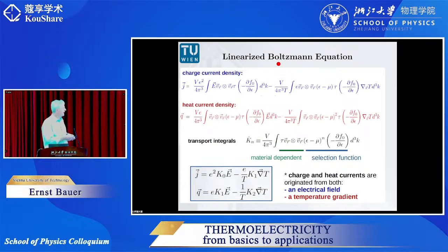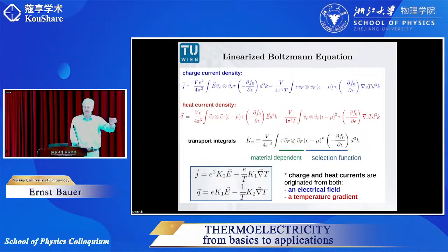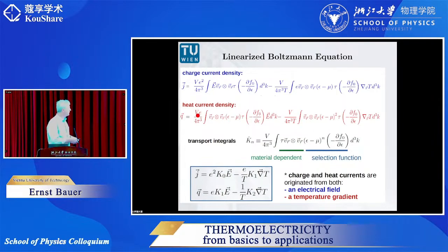And again, the linearized Boltzmann equation shows that the heat current density consists of a number of terms as well. And while we usually assume that heat is driven just by a temperature gradient from the hot to the cold side, you can see from this equation here, from the red colored equation, that heat is driven also by the electrical field.